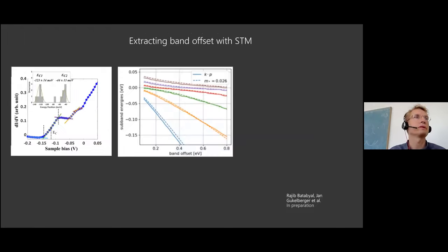Okay, move on here. So as I showed, in our laboratory we have this STM bolted on our fabrication tool, our crystal growth UHV line. If you go down and measure on an indium arsenide surface, this is grown by MBE, and then you measure the density of states with tunnel spectroscopy, you can see that you get some steps close to the Fermi level, and this is what we interpret as the confined bulk state. So this will be the first subband. It has a 2D nature, and this is the second one. And then it goes outside the Fermi level here.